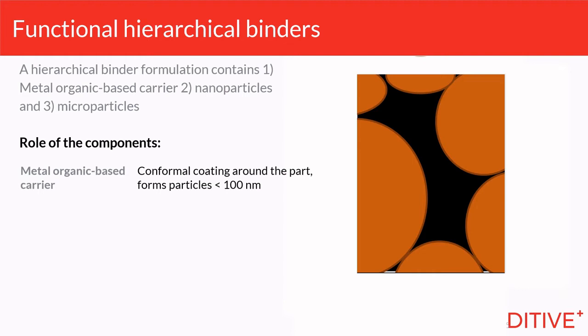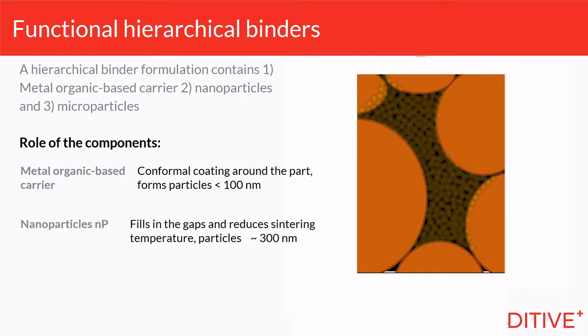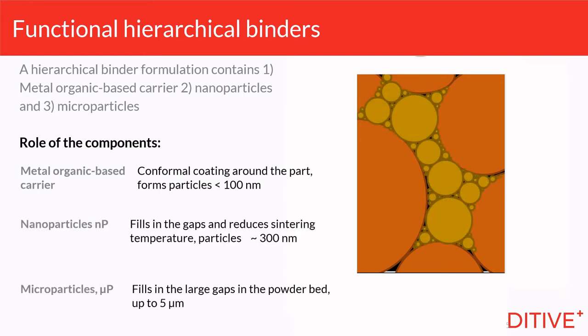And what's held in that metal solution is some nanoparticles. And the nanoparticles help to fill in the gaps and the interstices of the powder bed, but they also help to lower the sintering temperature because of this high surface area. And then finally, we've got microparticles. They fill in the remaining gaps, and they can be anywhere up to around 5 micrometers, depending on the size of your powder bed, depends on what size particles you can have in your binder. So we can see why it's hierarchical, because we've got molecular solution-based metal, we've then got the nanoparticle metal, and then we've got the microparticle metals, and they help to bind and also infiltrate the powder bed that you've got.